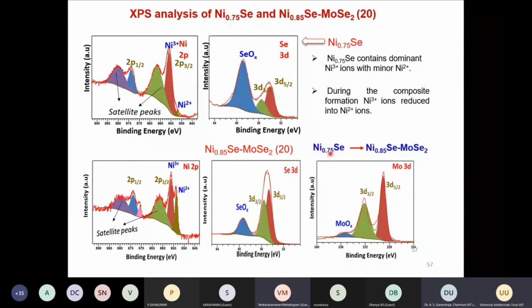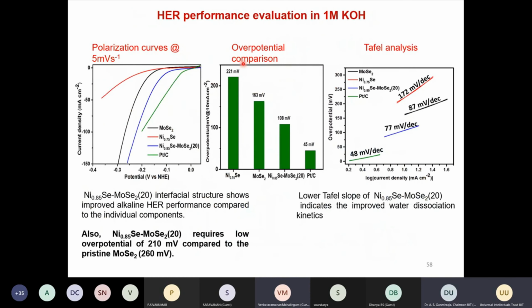So basically the Ni0.85Se has more nickel 2+, which is also reflected here. Of course, this selenium surface oxidation is unpreventable. This is another issue with the selenium, that you have this surface oxidation, which you can easily see from the XPS analysis.